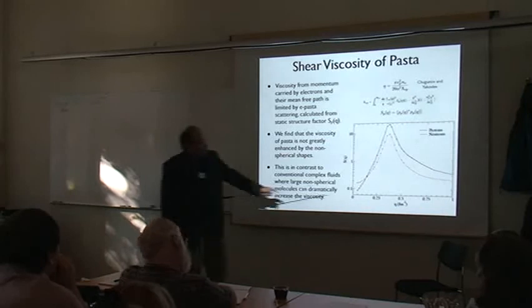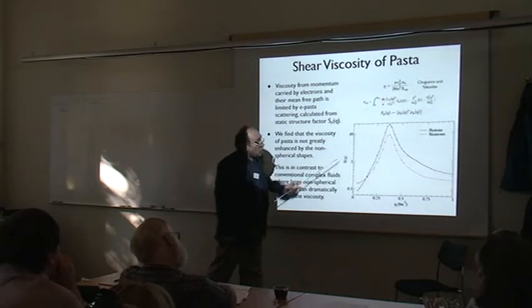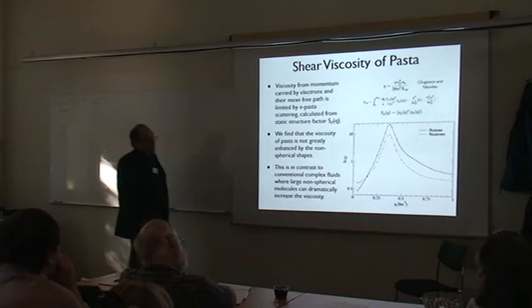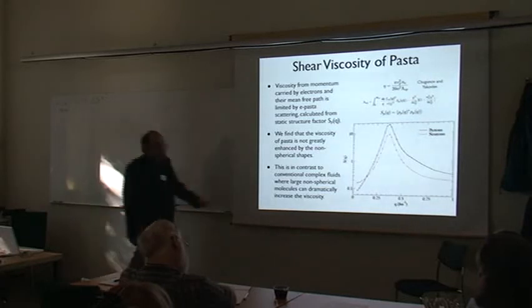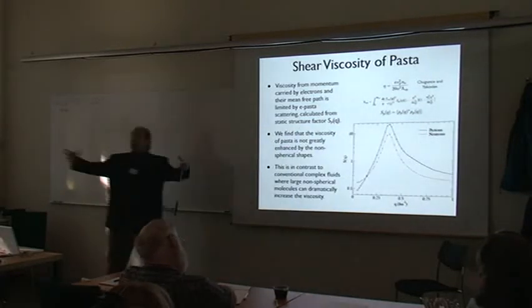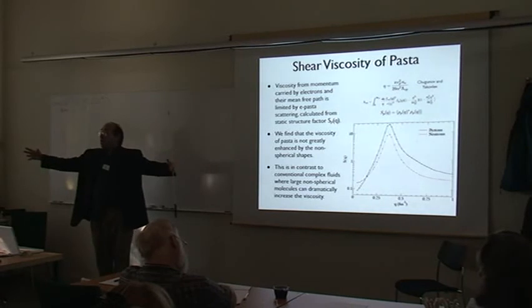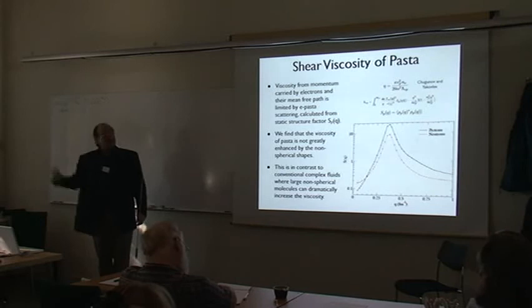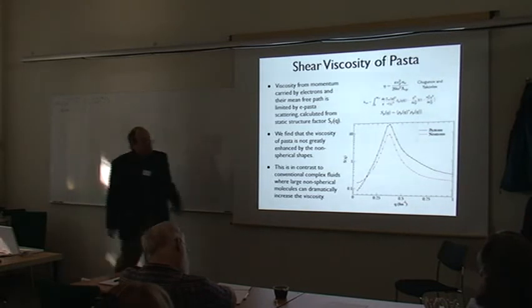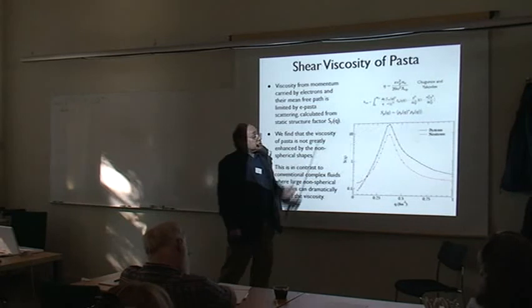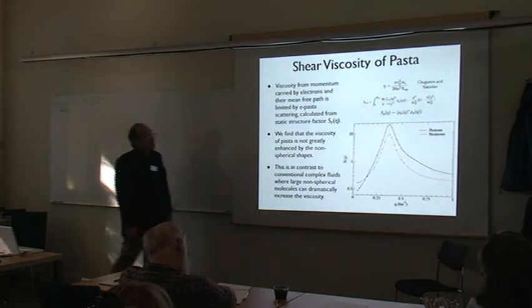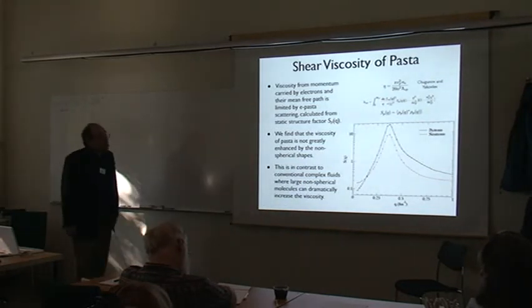So at low Q, S of Q is small because of ion screening. At high Q, S of Q is small because of the form factor. Pastas are big, so when you do elastic scattering from a big object at high momentum transfers, you only see a tiny fraction of the object. So there's some intermediate Q where you can scatter from as many as possible.